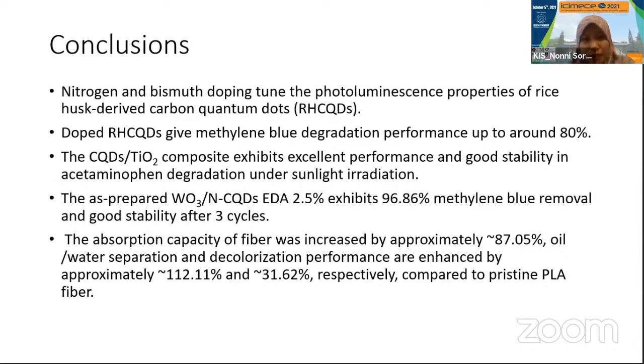So after 4 hours, we can degrade around 5 ppm of the acetaminophen. When we increase the acetaminophen to 10 ppm, we need around 6 hours to degrade the pharmaceutical agent under sunlight irradiation. Okay, so we also tried to combine the nitrogen-doped carbon quantum dots with tungsten oxide,